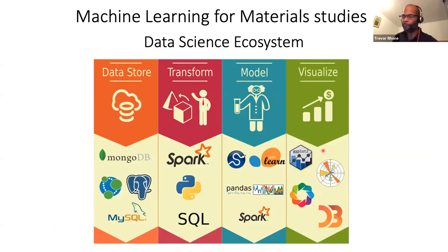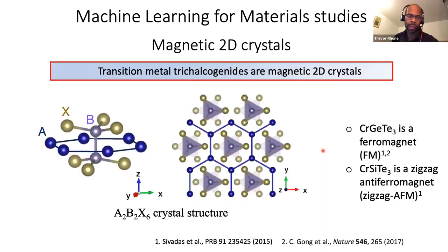So let's just change gears a bit and talk about a potential material system of interest. The one that I focused on in the beginning was this class of magnetic 2D materials that is based on these transition metal trichalcogenides. I think chromium germanium telluride is perhaps the most famous. It turns out this is a monolayer ferromagnet. It's predicted to be a monolayer ferromagnet, where the chromium atoms sit on the A site, the germanium atoms sit on the B site, here and here, and the tellurium atoms sit on the X site, so three above the plane and three below.